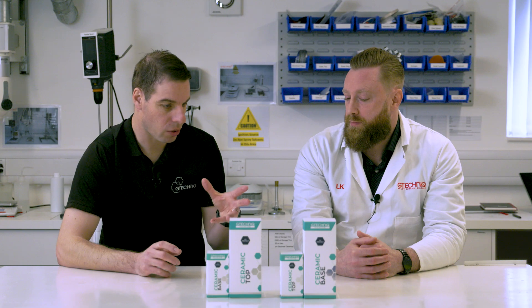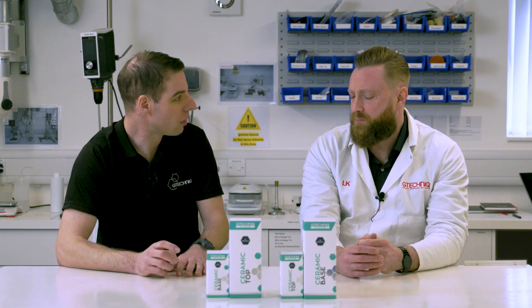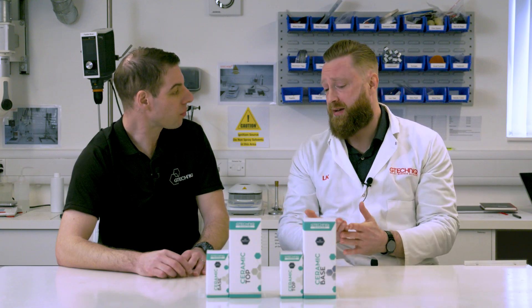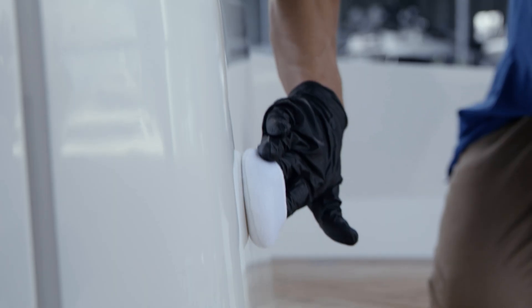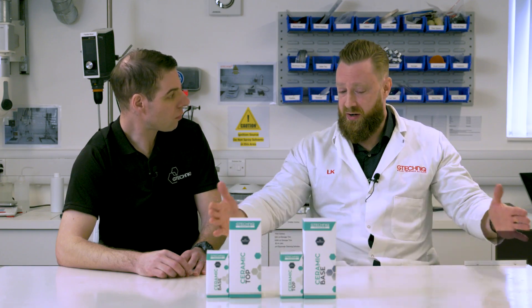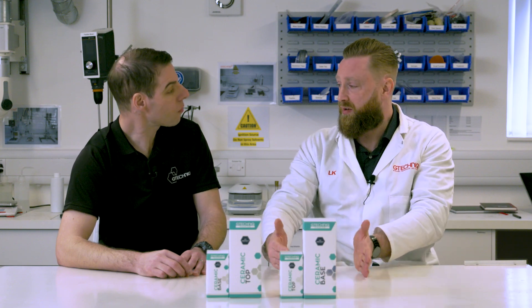In terms of the technical piece around how to apply them, they're actually not that difficult — I'd say easier to apply than wax and a more enjoyable experience. Each product comes with a little applicator pad; you simply wipe that onto the surface covering an area of around a metre squared, leave it for about a minute or so, then take a microfibre cloth and remove the residue working from the outside in. Flip the cloth over, go over again, then check for any high spots, flip the cloth a third time and buff it all off until you've got a nice clear finish. You then start the next section overlapping slightly and just work your way around the boat.